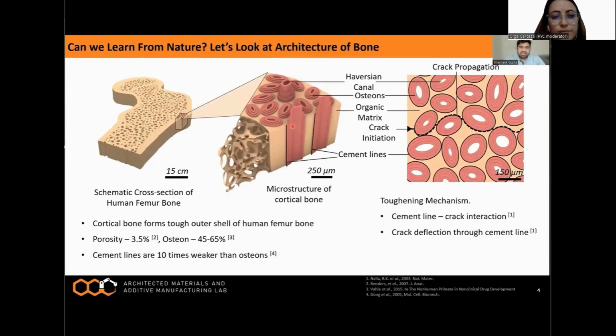These osteons are weakly bonded to the organic matrix through these cement lines. The cement line has nothing to do with the cement, just to avoid any confusion. The cement lines are 10 times weaker than the osteons. So when the crack starts to propagate in the cortical bone, these weaker cement lines provide a microstructurally preferred path for the crack to propagate, hence triggering toughening mechanisms like crack deflection through cement line interaction in cortical bone.